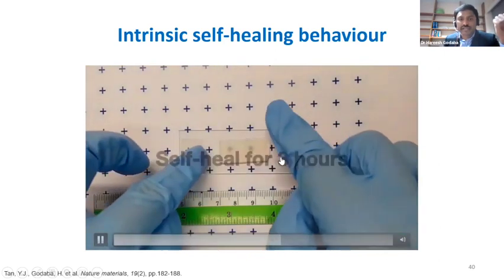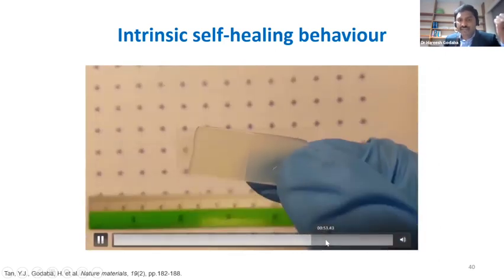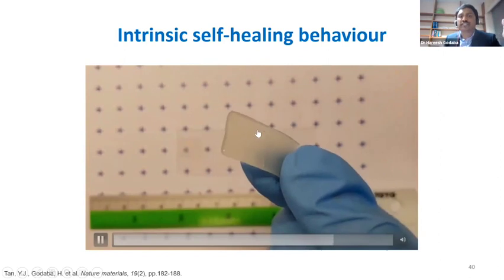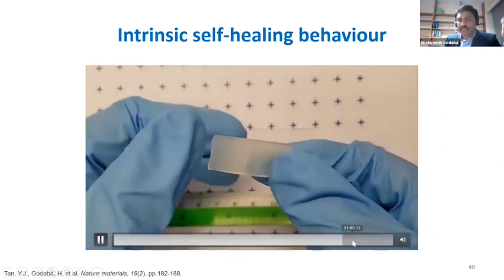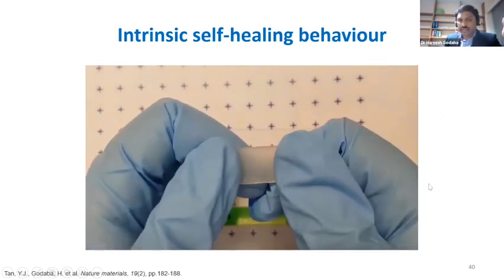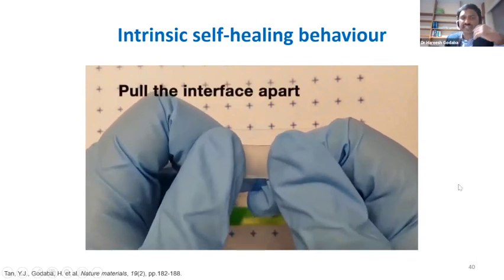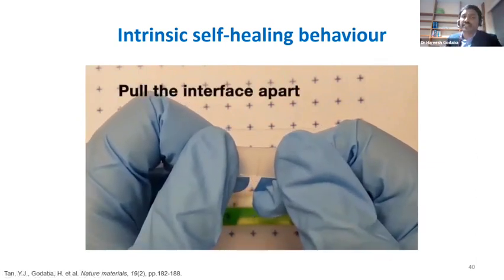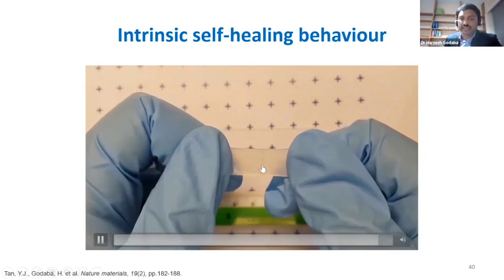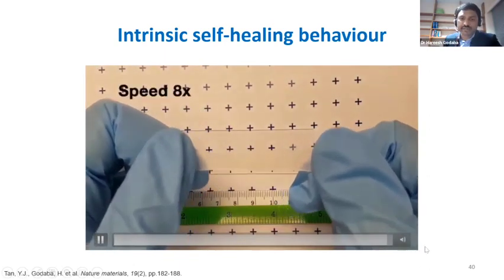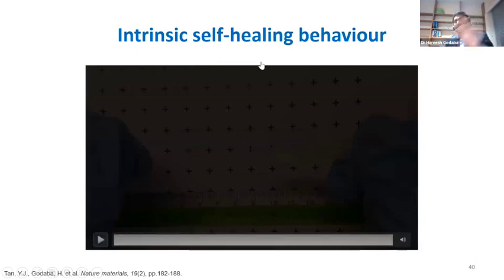Of course, if you leave it for 3 hours, you will see that the bond is now very strong, and you can see that it has significantly high strength at the interface, so that when we stretch it, the interface does not tear apart. So this is about the intrinsic self-healing behavior. So why we call it intrinsic is we do not need to trigger any heat or external stimuli like that for this self-healing behavior to take place.